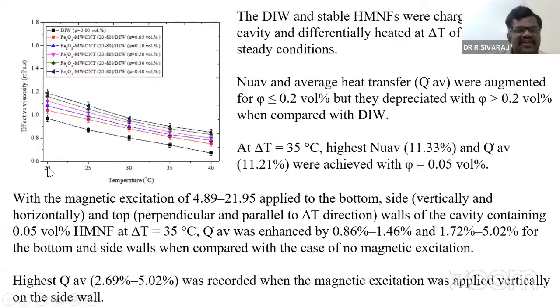It is obvious that if we increase the temperature, the viscosity will decrease. Then if we increase the nano-sized particles' volume fraction, it keeps on increasing the effective viscosity to a certain level. After 0.5, in general, it will not be accepted. In this case, maybe after 0.4 itself it may not be accepted. That's why they have stopped.